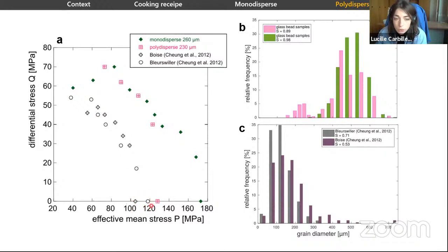But as we deform the sample under hydrostatic loading, P star is reduced as the distribution gets wider. So what we can say maybe is that it seems that pore dispersivity might have a different impact depending on strength, depending on the failure modes.